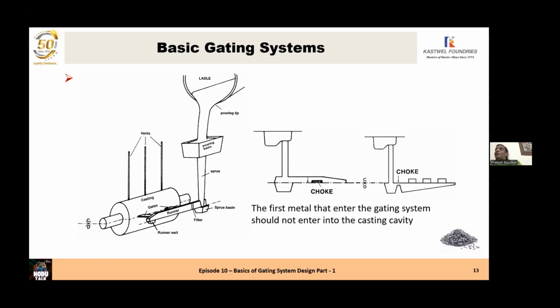As the metal leaves the pouring cup basin opening, it becomes narrower. And there's air between the metal and the sprue, and there's an aspiration, there's a vacuum, like a low pressure over there. And therefore, the air from the outside and from the mold is sucked into the sprue, and there's air entrapment between the metal and the sprue gap where the pressure is low. This air enters into the metal, and that should be kept out of the cavity.